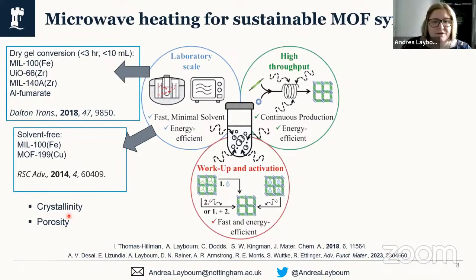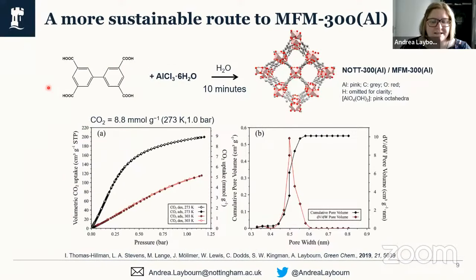And I also wanted to highlight a synthetic procedure that one of the PhD students in the group had developed. So this is the synthesis of NOTT-300 or MFM 300, which is made by reacting the biphenyl tetracarboxylic acid. We're using aluminium trichloride hexahydrate in this case. We're performing the synthesis in water in 10 minutes using a microwave reactor and off-the-shelf system. This produces the MFM 300 aluminium framework.